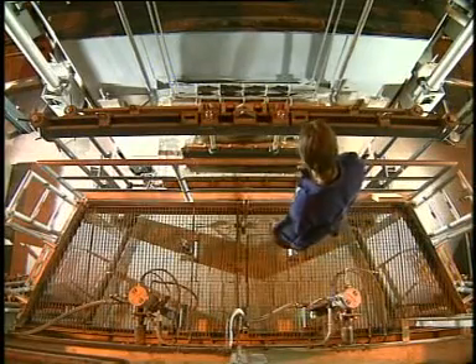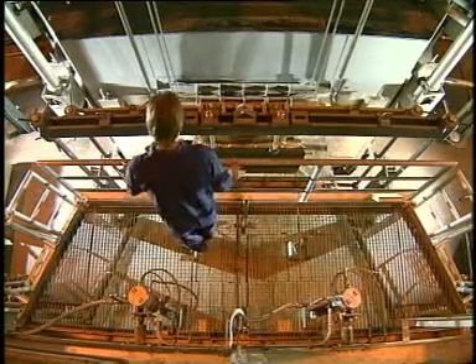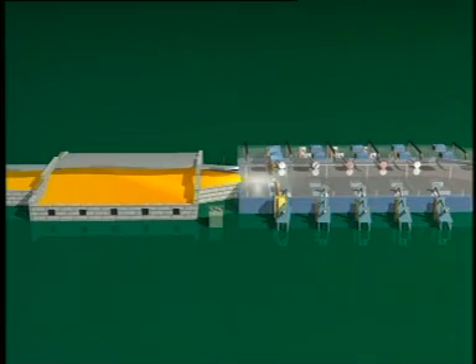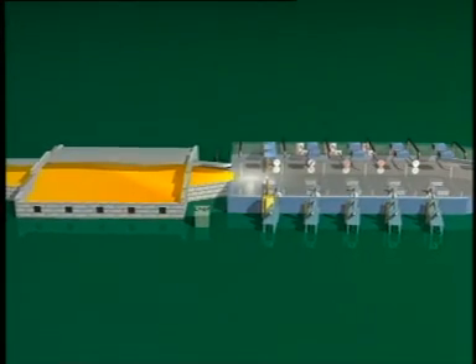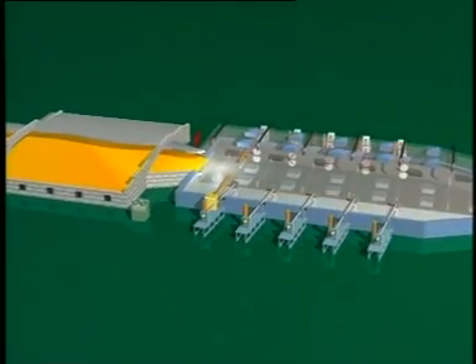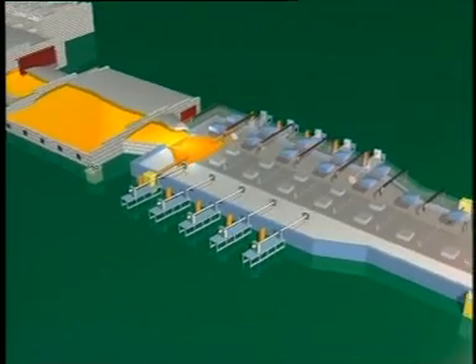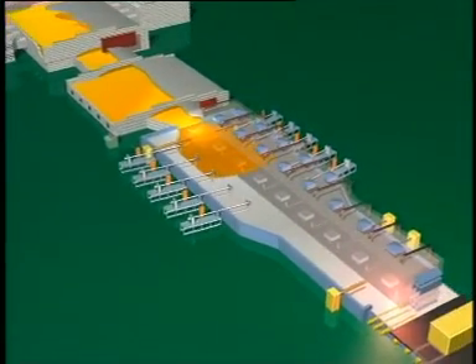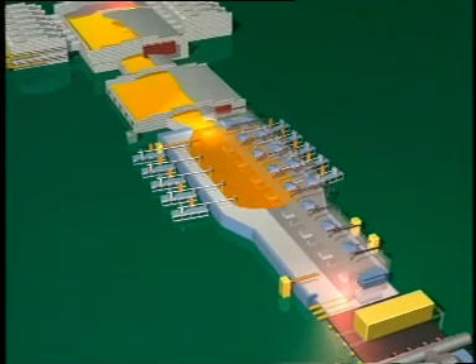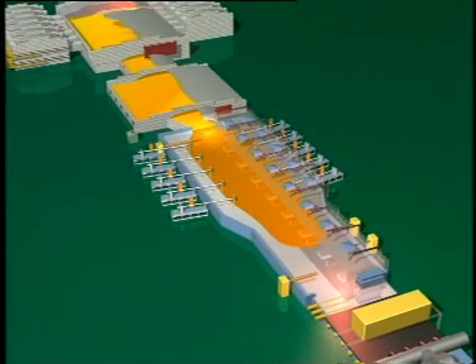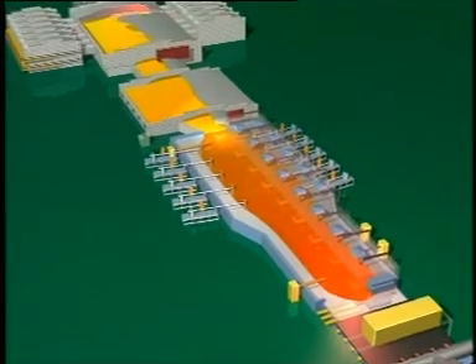Inside the furnace, heat is applied from alternate sides in 20-minute cycles. This assists fuel efficiency by ensuring that combustion takes place in the presence of preheated air. The glass leaves the conditioning end of the melting zone at a temperature of 1,100 degrees centigrade through a narrow canal, from where it passes to the heart of the process, a bath of molten tin. Here the glass spreads out, following the perfect flatness of the tin, so that the upper and lower surfaces of the glass remain absolutely flat and parallel.